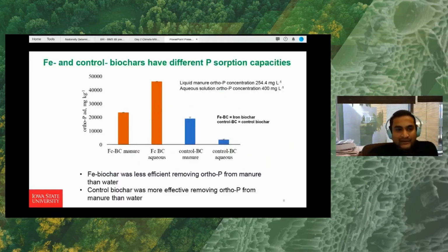Next slide, please. These are some results I'm going to present: iron and control biochar have different phosphorus absorption capacity. The orange ones are the iron biochar and the blue ones are the control biochar. You can see that iron biochar absorbs more ortho-P from the aqueous solution than from the manure, whereas the control biochar absorbs more phosphorus from the manure than from the aqueous solution. So the iron biochar was less efficient at removing orthophosphorus from manure than water, whereas the control biochar was more effective at removing orthophosphorus from manure than water. This shows the contrasting properties of the biochars we have used in this study.